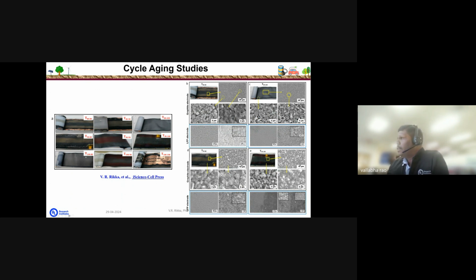To understand further the electrochemical side reactions, we have done the SEM characterizations, and we can see here the SEM morphology studies reveal that where the golden color is there, which is electrochemically active, in that area more SEI layer was formed, and where it is electrochemically inactive, the morphology is completely changed. This also clearly indicates that the non-uniform distribution of the charge hinders the rate performance of the lithium-ion cell. It can also cause localized heat generation, which can cause electrolyte evaporation over the cycles. That's why we identified the deformation of the jelly roll.